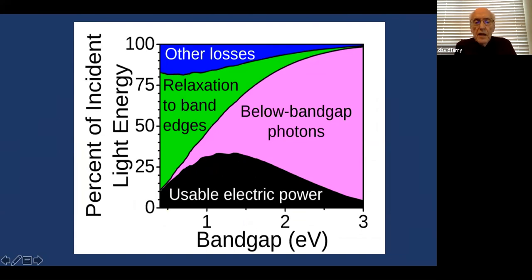at your cell. Okay, now if you raise the band gap of the material too much, you lose this part of the solar spectrum. And so you can't get any energy out of all that light that's coming down with these photons below the band gap. So that's not good. The green part is what we're trying to worry about. The green part is what's going to be our phonon losses, relaxation of band edges. I'll explain that phrase in a little bit. And this is other losses, reflection at the surface, metal blockage, things like that.